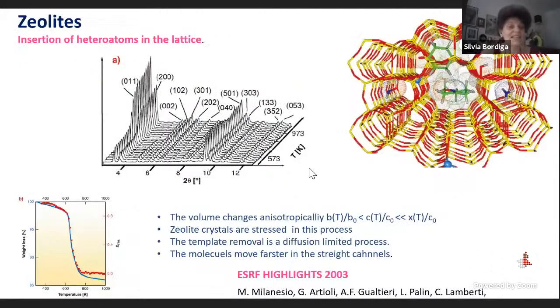Another possibility is to develop zeolites where we have a substitution of heteroatoms. And in the past, in Turin, but not only in Turin, we had some work together with the friends in Alessandria, the study of TS1. In this study, for instance, is reported the effect on the lattice change, introducing titanium inside the lattice of the silicalite in the MFI network.